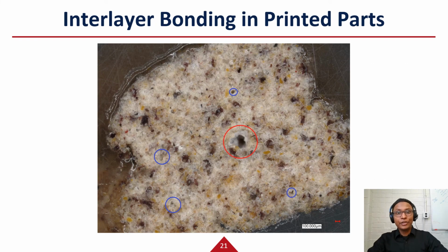Let's recall the third requirement for printability. We wanted strong bonding among different layers. Here you can see an image of a multi-layered part after sintering. Different layers fused really well. Small pores are distributed across the whole part and not confined within the layer gaps. So we can say that our developed material is also printable because we were able to achieve good interlayer adhesion.